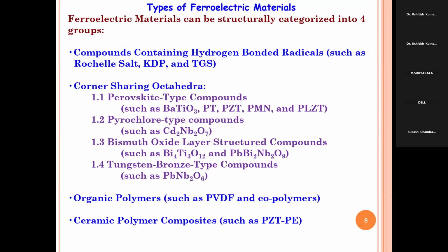And not only the perovskite material, the bismuth oxide layer structure is also a very good material, and people are also working on tungsten bronze type materials, and on pyrochlore type compounds. But as so much research is going on perovskite material, we are thinking about the bismuth layer structure compounds. We are trying to prepare this type of material, and we have also characterized all the different properties I told you about: how much ferroelectric property, how much piezoelectric property, and what the dielectric constant of that material is.